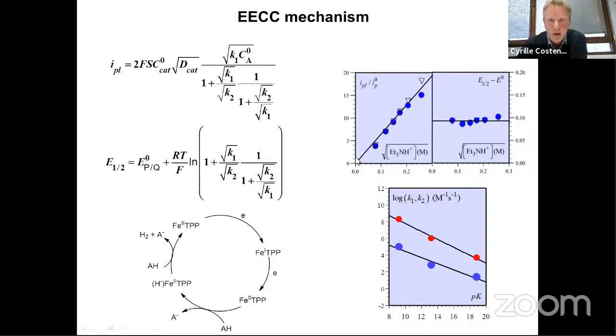As you can see here, the plateau current is actually proportional to the square root of the concentration of acid, here protonated triethylamine, as expected, whereas the half wave potential is independent of the concentration of acid, but it's not equal to the standard potential, okay? It's 100 millivolt more positive, which means that from this position, you can get the ratio K1 over K2, and knowing the ratio K1 over K2, from the plateau current, you can get K1, and once you have K1 and the ratio K1 over K2, you get K2. So you can get a full characterization of the catalytic process.